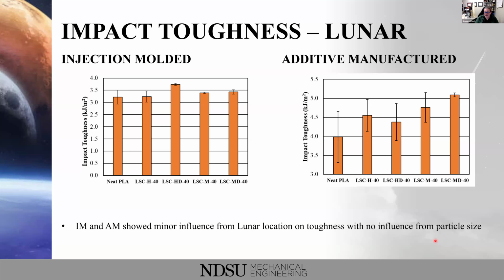For our lunar, very much what we expected to happen. Our impact strengths changed a little bit when we went from injection molding to additive manufacturing. We had minor influences from the lunar location on toughness, but particle size did not have an influence, which tells us that we don't need to take that extra step of trying to sieve the regolith down into a much narrower particle distribution. We can just take it as it is off the planet and turn that into usable materials, and have relatively good mechanical properties in terms of the neat polymer.